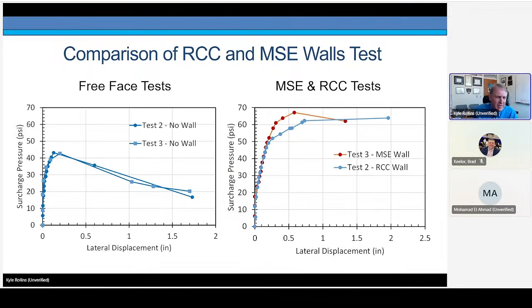This is a comparison of the surcharge pressure versus lateral displacement curves for the two cases where there's no wall. And even though the strength is a little bit different, two different tests, the surcharge pressure versus lateral displacement curves with no wall in place are very similar. Likewise, with the MSE and the RCC tests, the surcharge pressure and lateral displacements are very close to one another. The RCC developed its resistance a little more gradually to get that additional resistance, whereas the MSE reinforcements pick up resistance faster and then have a little bit of a drop off.